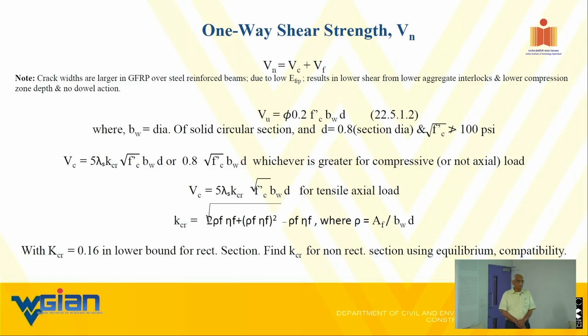In our code there is a concrete strength which takes the combination of dowel and interlocking and some other factors, the percentage of reinforcement and also the concrete strength. But we don't consider any dowel force. Actually, bond is less for GFRP with concrete, I think. No, bond of GFRP and concrete is slightly higher than that of steel and concrete. For design purposes, we don't differentiate any major difference in the bond strength. In other words, we assume bond strength is the same, even though bond is slightly higher in GFRP than in steel. For design purposes, we assume the same.